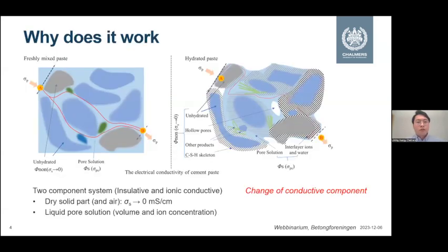I also want to say some words about why conductivity works for monitoring performance, like strength and durability index, because we can simplify a concrete system into 2 main components: the insulative and the conductive. The insulative part is mainly the dry solid, and also includes some air or empty pores. The other part is conductive, and we can classify it as liquid pore solution. Of course, we include some interlayer water from the CSH or other layered hydration products, but to simplify, we classify them into the liquid pore solution part. So during hydration, drying or the ingress of chloride, the volume of the conductive component and also the concentration will change, so that we can follow them by the conductivity change.